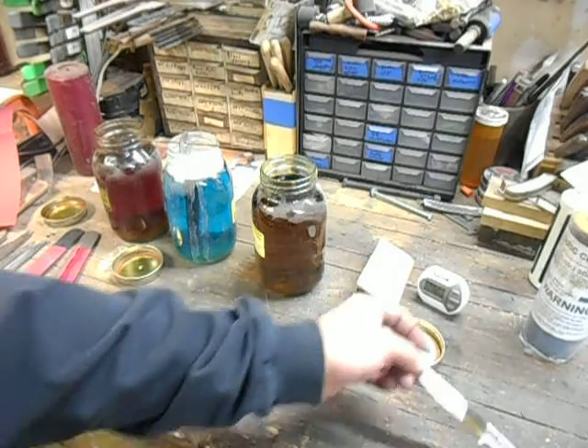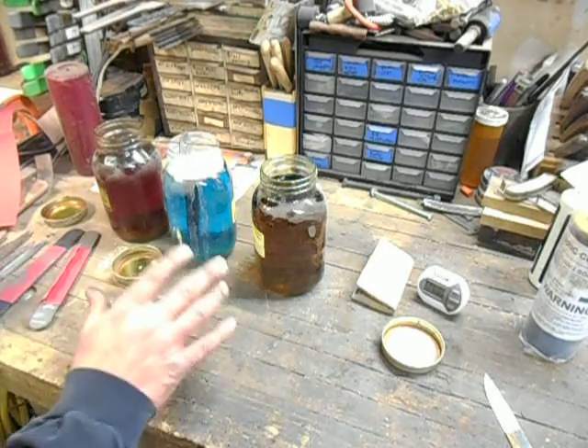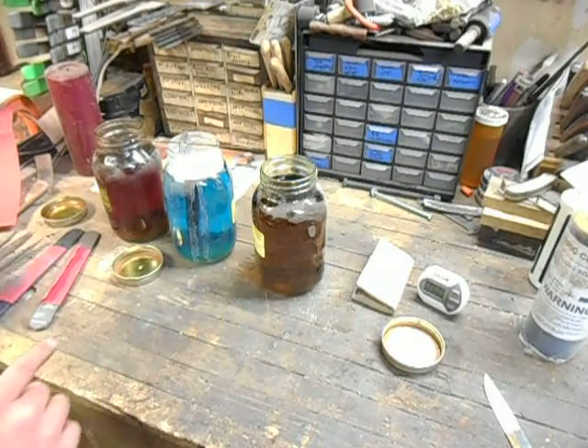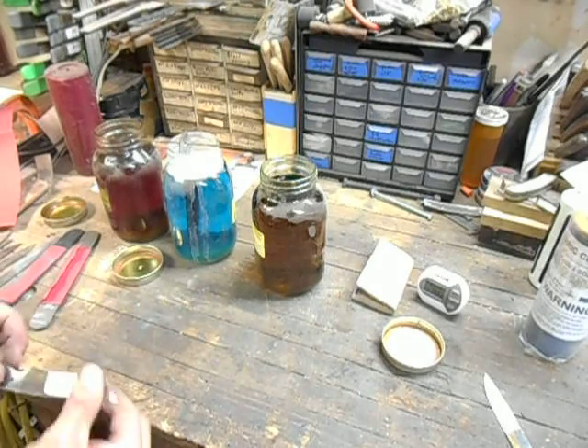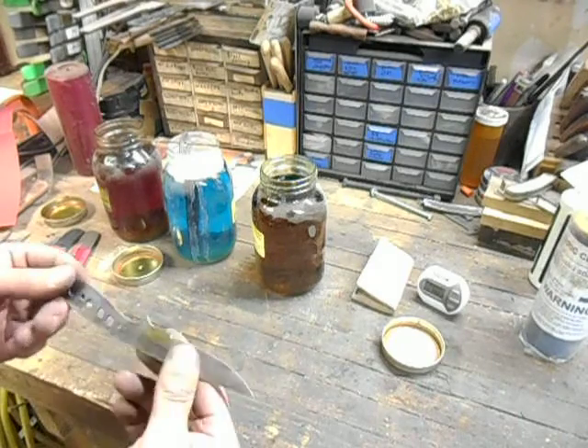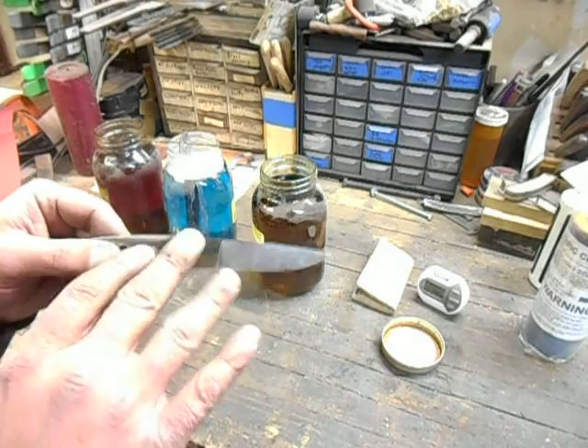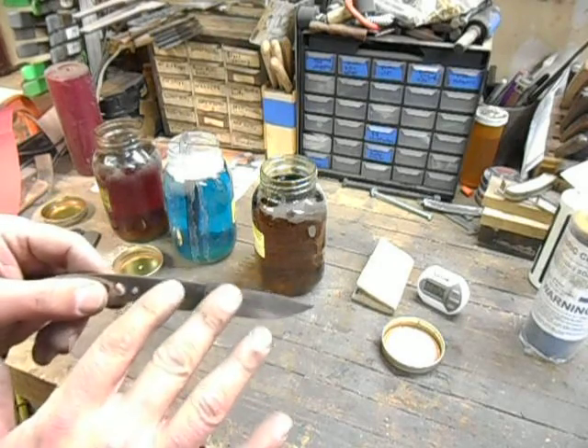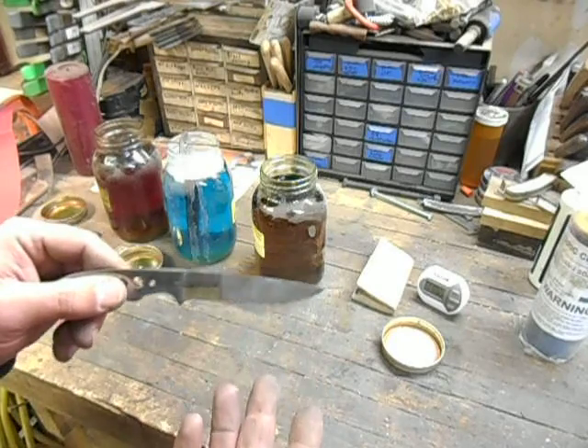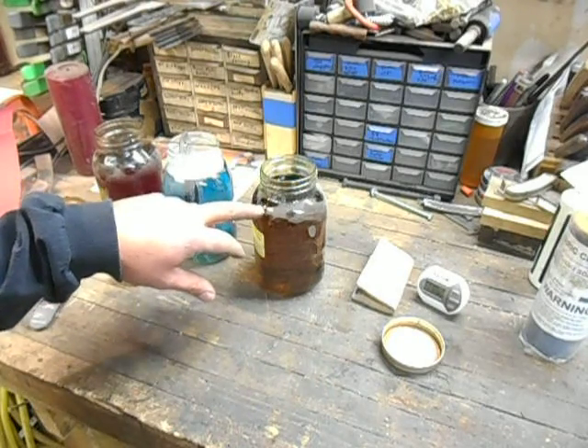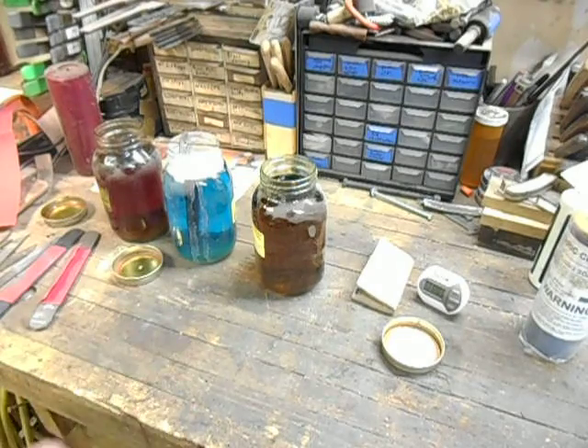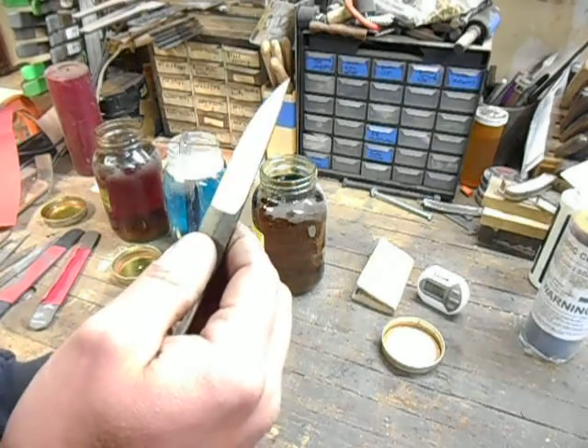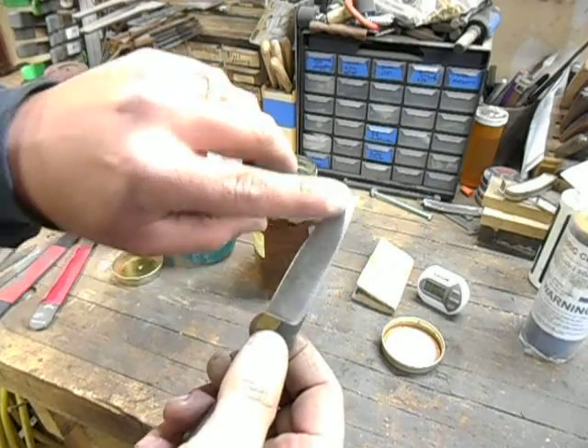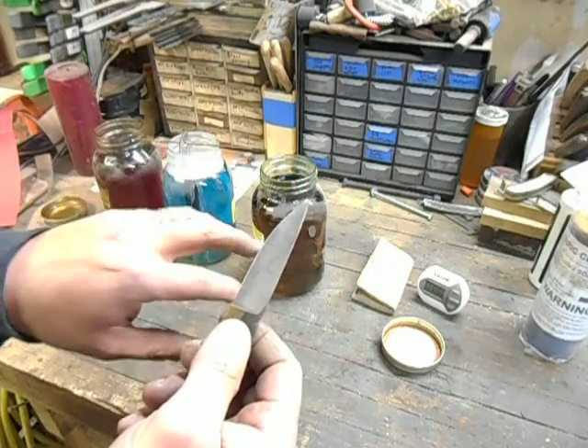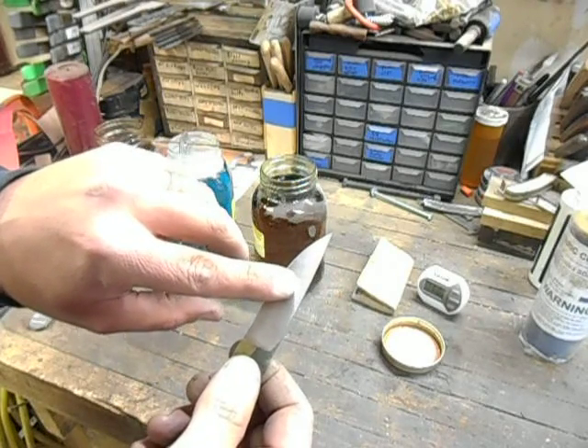It's amazing. So anyway, prep work before you etch a blade. What we're doing now is we're etching that blade that I hand sanded to 400 grit in the hand sanding video. But you take your blade, let's say whichever one, and I hand sand them down to 400, 600, sometimes I might go to an 800 grit finish. It seems to me like the 1:4 mix of ferric is about a 600 grit etch. So what I mean by that is if you have 600 grit lines running on your blade, that etch will eat those 600 grit lines away.